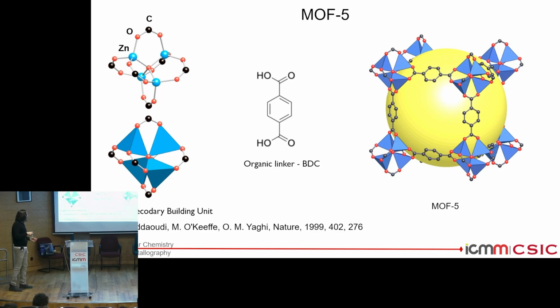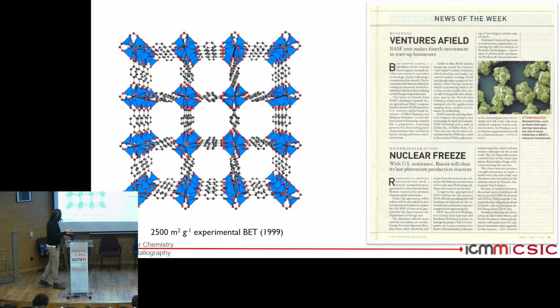So MOF-5, published in 1999, had these building blocks based on zinc carboxylate clusters and this benzene carboxylic linker. So very simple building blocks, but when you have them together, you have a structure that is very, very porous, actually. And in this one, following this approach based on the carboxylate linkers, the material could be fully evacuated. The first surface area reported for this compound, MOF-5, was 2,500 square meters per gram.